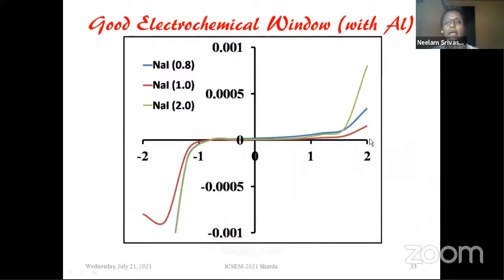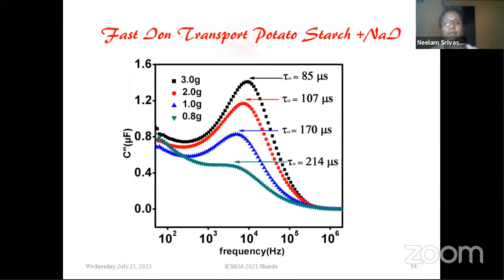This is the electrochemical stability window, quite long, quite wide, that's very good. The electrochemical stability window changes with the salt concentration. As you increase the salt concentration, it slightly decreases, you can observe, but it's okay. There is a compromise between the conductivity and electrochemical stability window as you increase the salt concentration. So it is up to you what range you want for your device. You can play with the salt concentration and get the kind of parameters you need according to your device application.